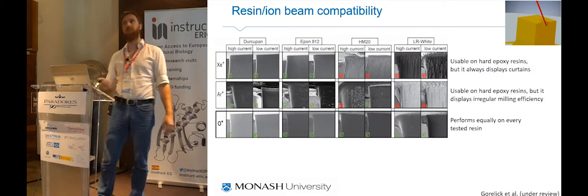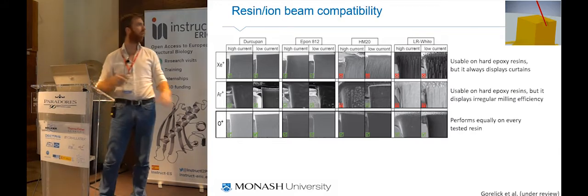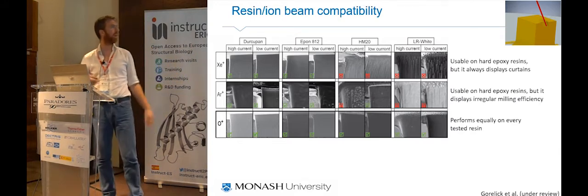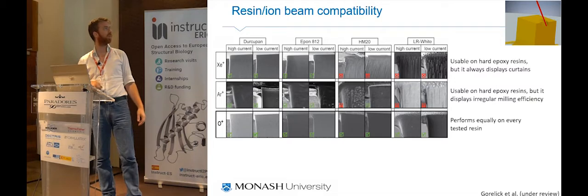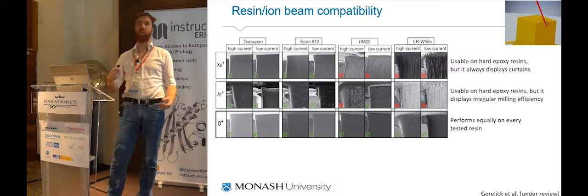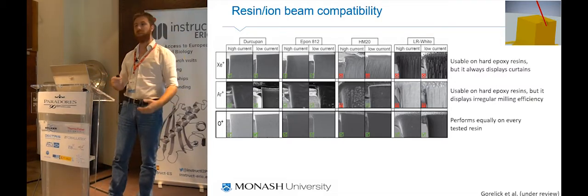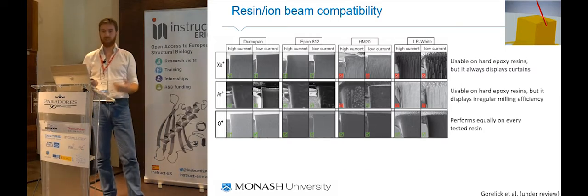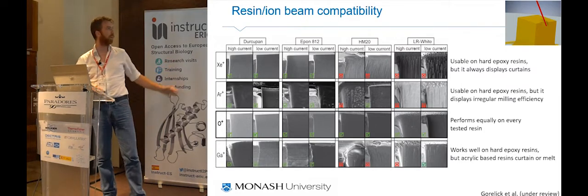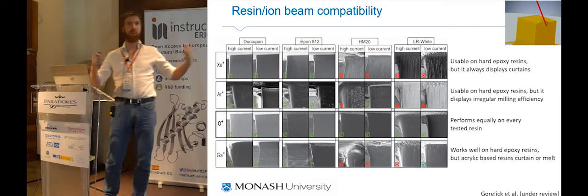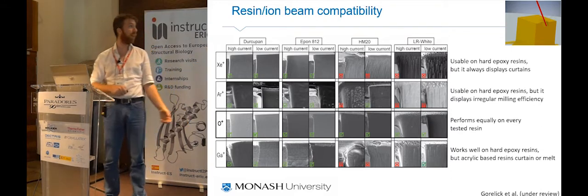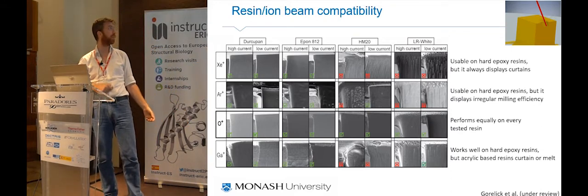Then we went to oxygen, because we thought, it's carbon-based, let's do some etching. It works beautifully throughout. Everything is just fantastic. No matter what current we used and no matter what material we used, the cut face was always curtain-free. This is really promising. Then we compared it to gallium, because gallium is the benchmark, because everybody's using gallium. And we found that essentially gallium behaves very similar to xenon.